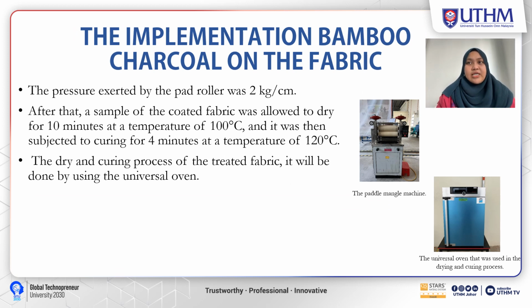Next, the pressure exerted by the pad roller was 2 kg per cm. After that, a sample of the coated fabric was allowed to dry for 10 minutes at a temperature of 100 degrees Celsius, and it was then subjected to curing for 4 minutes at a temperature of 120 degrees Celsius. The drying and curing process of the treated fabric will be done using the universal oven.